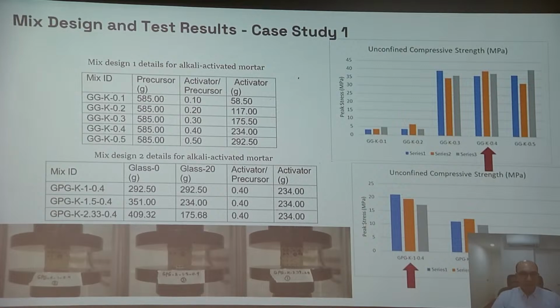Then we further analyzed the particle size distribution of the precursor, and the optimized version was the one that used activator to precursor of 0.4 and the ratio of ground glass 0 and ground glass 20, which are two different particle sizes of ground glass as precursor.